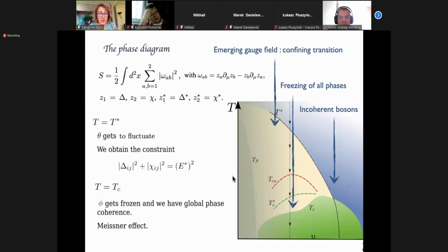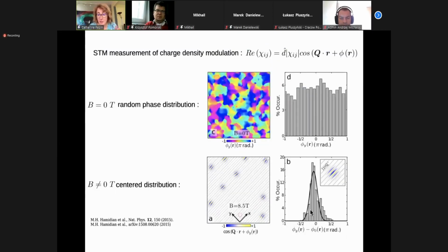But you see, those two orders are very weird. One is neutral to the electromagnetic field, which is the charge modulation. The other one, the delta, is active to the electromagnetic field. You put in an electromagnetic field, you get the Meissner effect. So below Tc, since the phases of the two get locked and freeze, this one will become active. So in terms of symmetry, the charge density wave will become like a pair density wave. So it's a reconfining in a sense. Despite that, we get long-range coherence of the phase because it is locking to superconductivity. That's our idea there. We get it for free, with this idea of locking of the two phases.